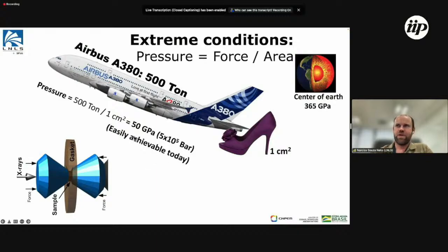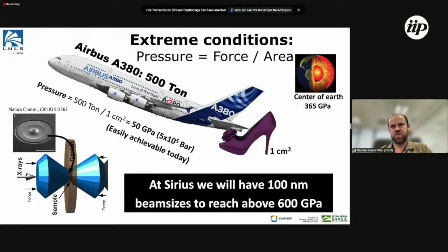the airplane to achieve those pressures, and basically what we have are two diamonds. So we use these two diamonds with a very small area, on the range of tens of micrometers. And we apply a lot of force on the diamonds because diamond is very hard. Actually, we can achieve those kinds of pressures in this way. Then we put a sample in the middle between the two diamonds and go with X-rays so we can do experiments and see what is happening to the sample while changing the pressure on the system.